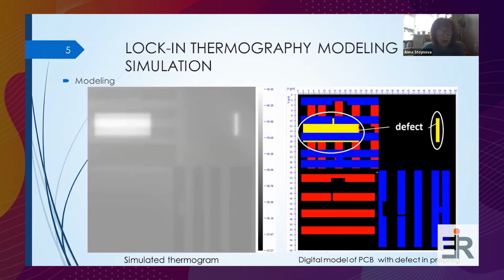First of all, we have Prepreg test samples with artificially manufactured defects of cavities in the dielectric Prepreg layer. One important feature of the samples is that the topology of the copper foil has been formed.